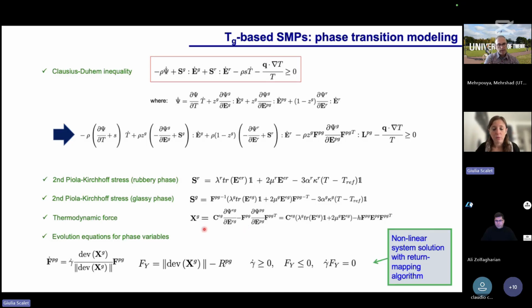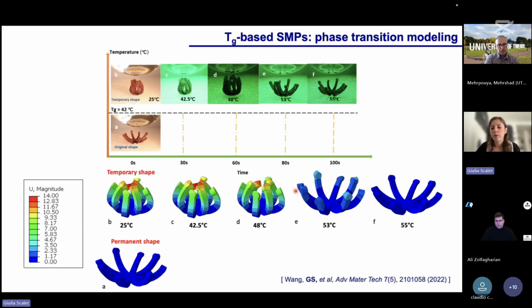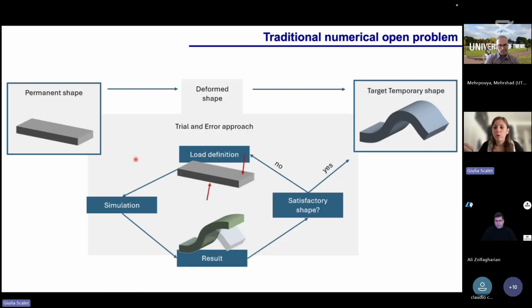We did it in Abaqus software, and you can support the prediction of the behavior of this structure by numerical simulation, and the comparison shows very good results. The main problem we face with, for example, this structure, but also other structures, is, as you can see, you start from a permanent shape and you have to deform the structure to a temporary shape. So you have to apply, first of all, a mechanical deformation under isothermal condition at the beginning. And this is the first step of the programming step. And this is, let's say, challenging from the numerical point of view because you don't know a priori the boundary condition to apply in order to get the right target temporary shape.